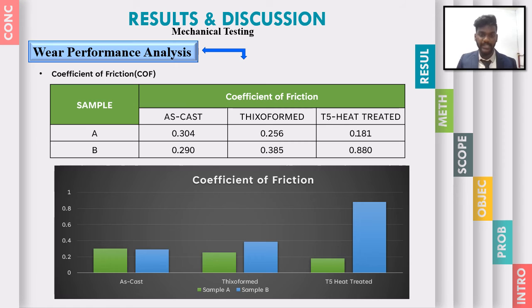So we can conclude that sample A is very good resistive towards friction, because the values decrease at each stage from S-cast to thixoform to T5 heat treatment, while for sample B the coefficient of friction index is slightly high at the third part, where the T5 heat treated sample has 0.8, which is nearly going to be 1 for coefficient of friction. That is not really recommended.